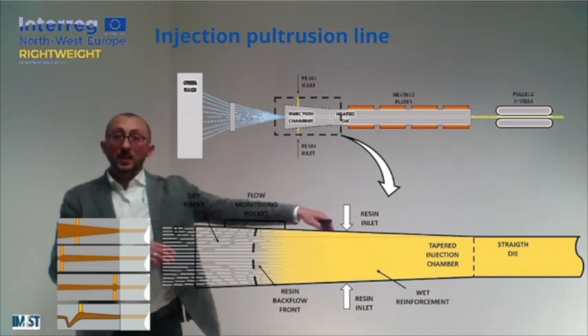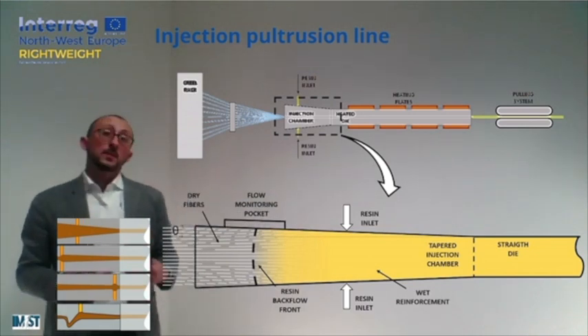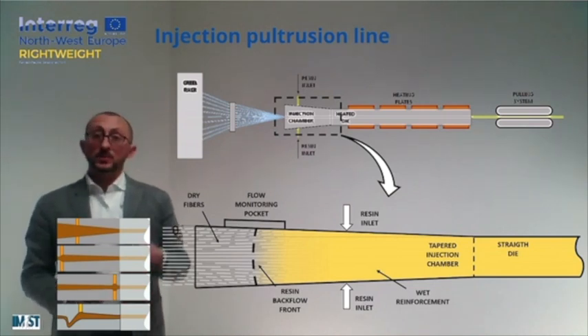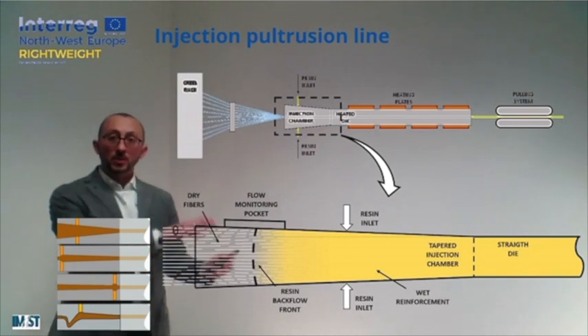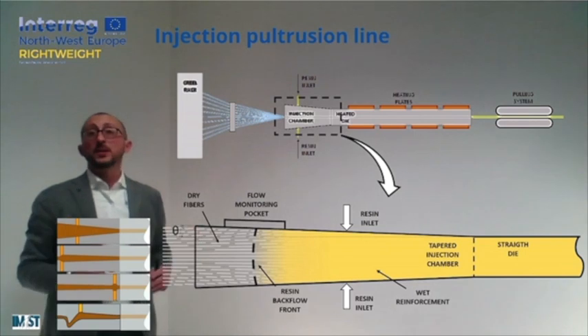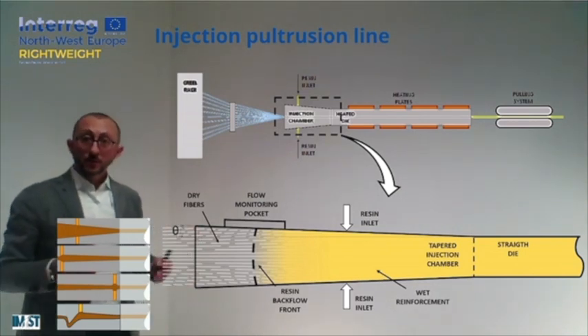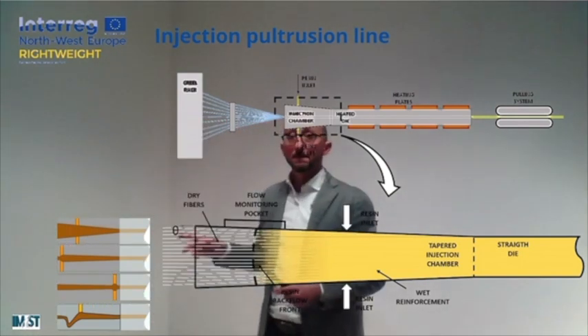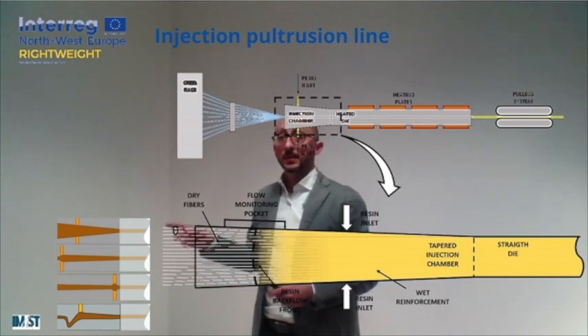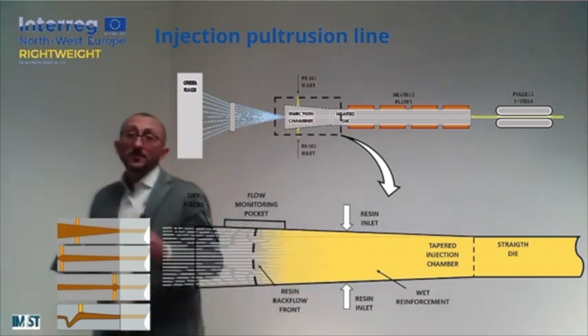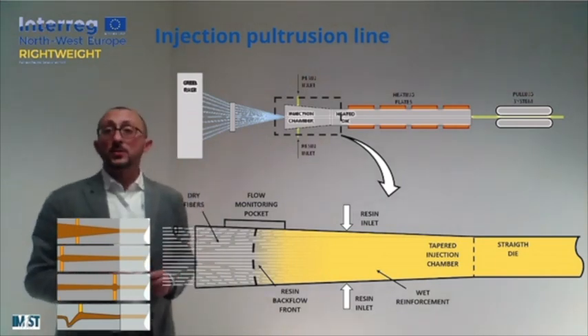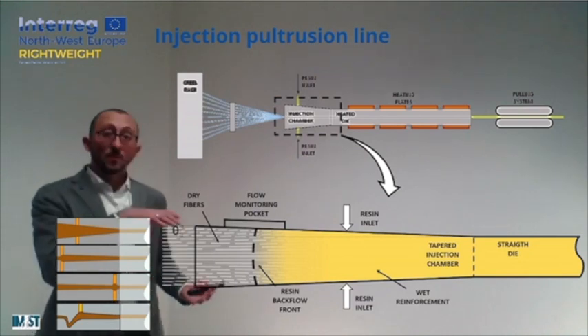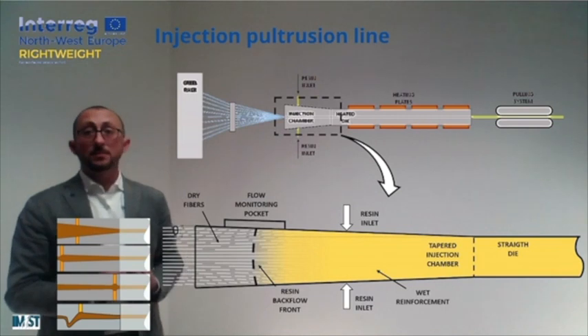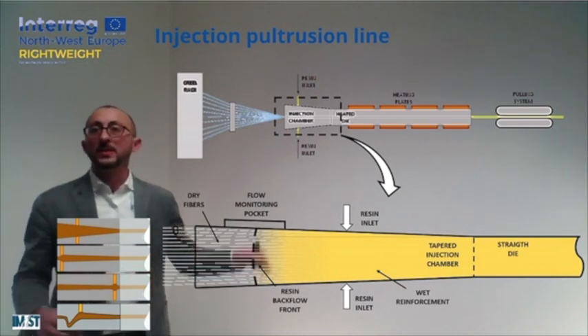This injection of resin will give us the possibility of wetting the reinforcement and achieving the impregnation stage just a few seconds before moving to the shaping and solidification. The specific configuration of the injection chamber should follow this kind of schemes that you can see here, moving from the very simple one that is the tapered chamber. Then other possibilities are the teardrop chamber, rather than high pressure or siphon chamber. So different possibilities that are designed in order to promote the same effect: compaction of the material, increasing of the resin pressure, and in order to promote some flow of the resin through the preform.